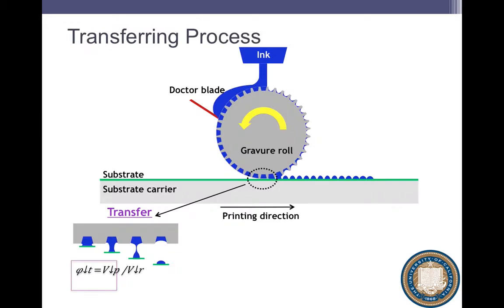And transfer is also sort of interesting. It turns out experimentally it's really difficult for us to measure transfer in line. We can measure it after the fact. But it's been really well modeled theoretically, and it turns out experimental results sort of back this up. I won't go through the details, but it turns out transfer also works better when you go fast. And the reason is that the fraction of transfer depends on this bridge that forms between the two, and the amount of ink that gets deposited versus held back in the cells depends on how quickly those lines move on the substrate. So if you go fast, it gives them less time to move, and so you can transfer more ink.